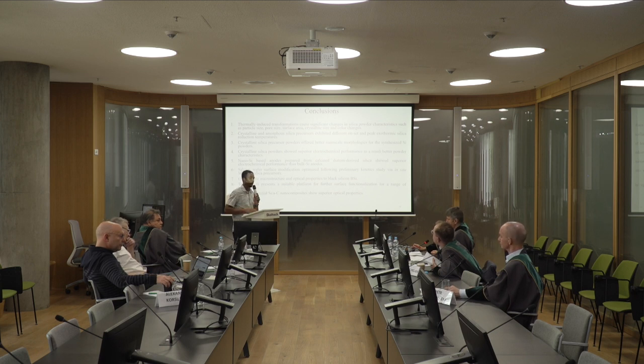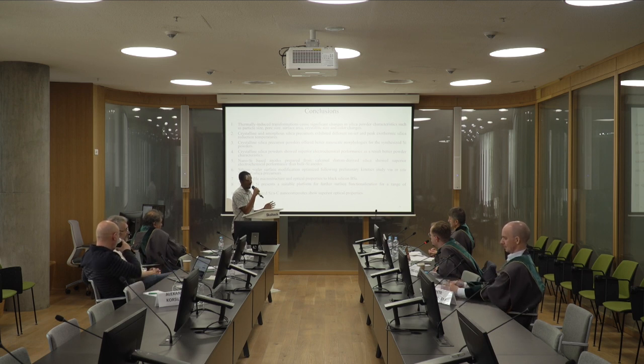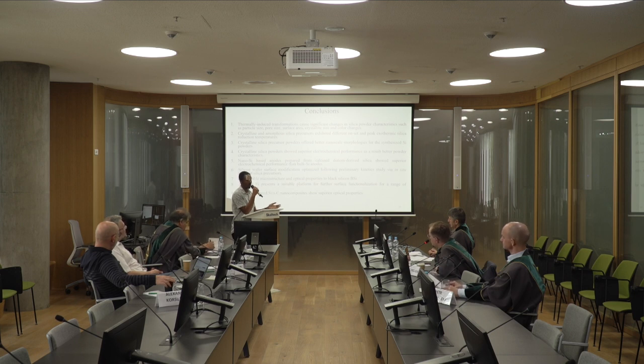Okay, thank you. And the last question would be regarding the last point in your conclusions, regarding the superior optical properties of nanocomposites. So what does it mean, superior? Can you elaborate on that? So superior, point 9, right? Yeah. Okay, thank you. So superior in the sense that we have improved optical absorption, light absorption over a broad range of the electromagnetic spectrum for the bilayer textured silicon and amorphous carbon composite compared with just textured silicon, because for textured silicon we have good absorption in the visible range, but this drops at longer wavelengths. So that's what we mean in point 9. Okay, thank you very much.